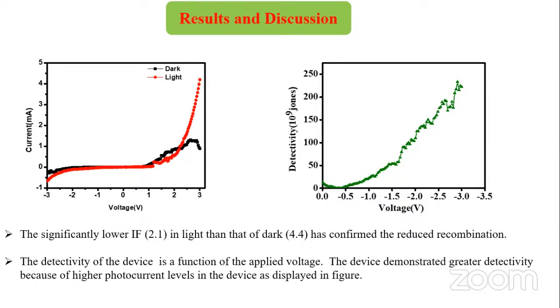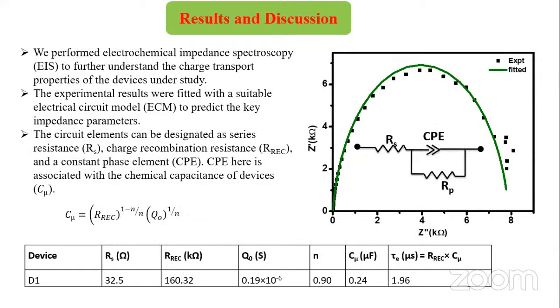And next is the result discussion for the electrical properties, where we can clearly see that the increased photocurrent is observed in the condition of illumination, and the ideality factor is reduced under illumination because of the reduced recombination. And the detectivity of the device is a function of applied voltage. So here we can see the increased detectivity of the device. And similarly, the impedance parameters are shown clearly, which shows the increased lifetime of the charge carrier.